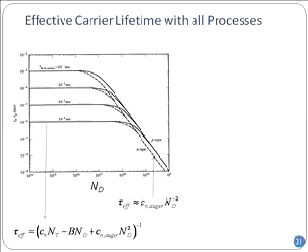Now if you go to a very high doping side, then the first and second term will drop out. Why? Because these are actually smaller terms. The third term will now be humongous because it's nd squared. Now remember, this is a log-log plot. So if you take a log-log on the tau effective on the left and right hand side, what should be the slope of that line? -2, right? If you look at this curve, you will see -2 is exactly the value on this curve. The slope on the high side is exactly that.